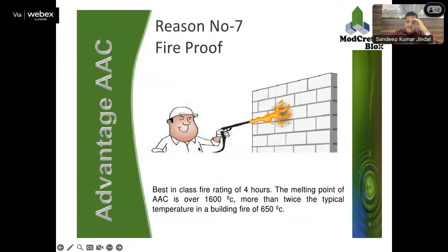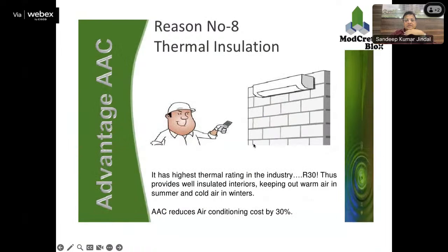Fireproofing is another attribute which is quite good for this product. Normally, the fireproofing rating for red brick is 2 hours. For this particular product, it is 4 hours. So it is double that of red brick, if I compare with red brick only. Thermal insulation is R30, which is quite good in fact in this product.